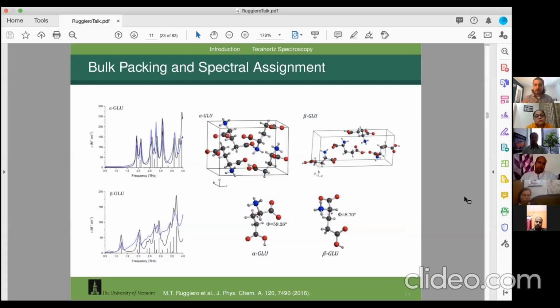So if I made these two crystals, which I can in the lab, they're stable and I can make them, and I bring them to an FTIR, I'll see basically the same spectrum for the two of them. There might be some slight shifting of one peak by a few wave numbers. The same thing with Raman. If I put it in a Raman spectrometer, they'll look nearly identical, maybe slightly different, but hard to discern. But what you see here on the left are the terahertz spectra in blue, and they're completely different. There's no question, the beta form has a big peak right here that doesn't exist in the alpha form at 1.3 terahertz.